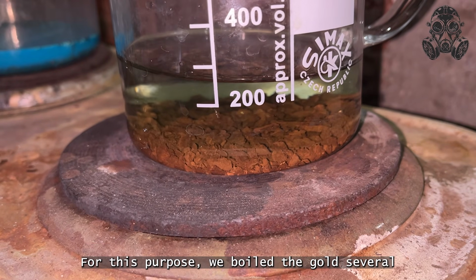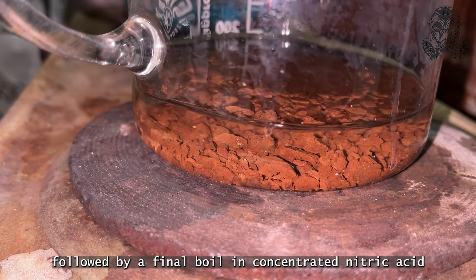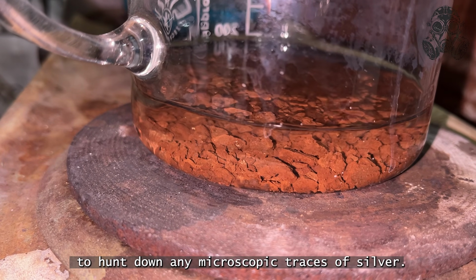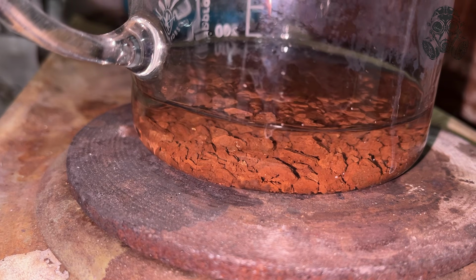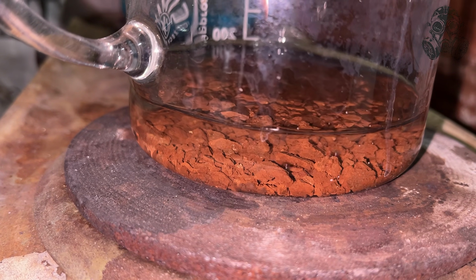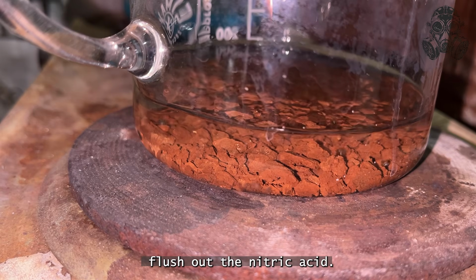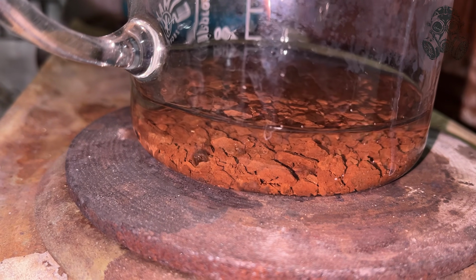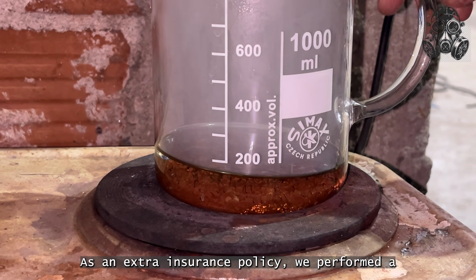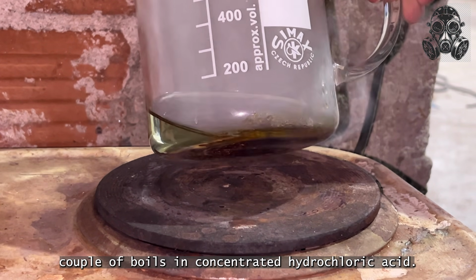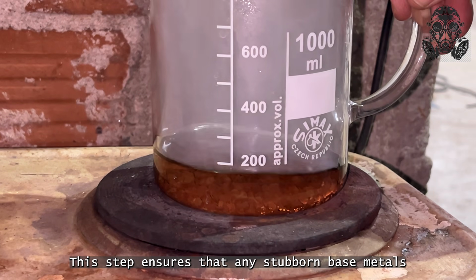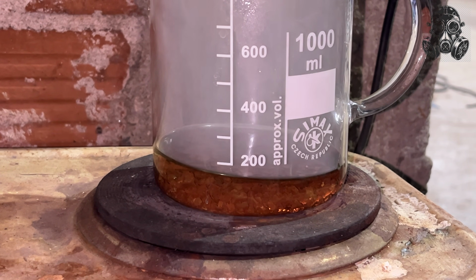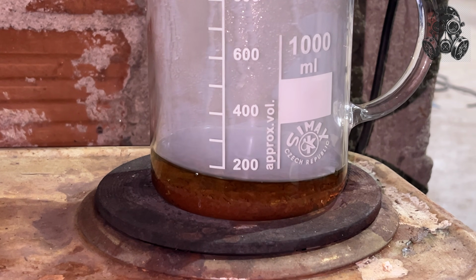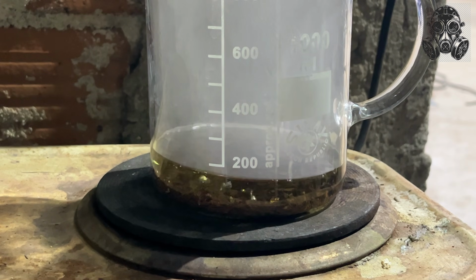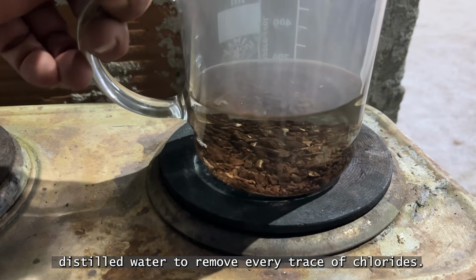For this purpose, we boiled the gold several times in distilled water, followed by a final boil in concentrated nitric acid to hunt down any microscopic traces of silver. We then returned to distilled water to thoroughly flush out the nitric acid. As an extra insurance policy, we performed a couple of boils in concentrated hydrochloric acid. This step ensures that any stubborn base metals or iron are stripped away. Finally, we finished with several boils in distilled water to remove every trace of chlorides.